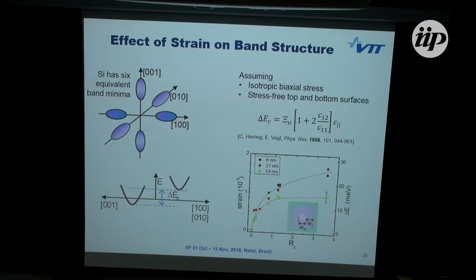This, of course, has an effect on the band structure. So this is a band structure of silicon. There are 6 equivalent band minima. And when this in-plane strain is applied, it means that these two out-of-plane valleys, their energy goes down a little bit, and the energy of these valleys increases a little bit. So there's a splitting of these band structure energies. And the split is a few tens of millielectron volts. So it's about the order of kT.